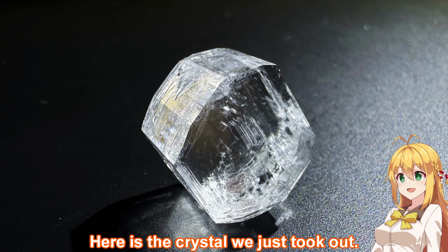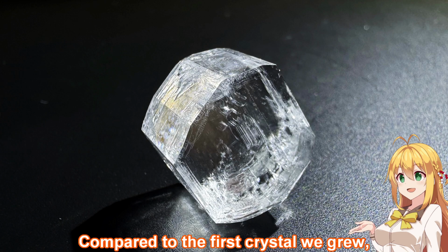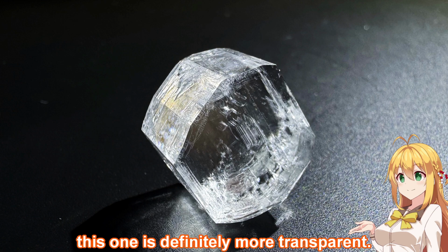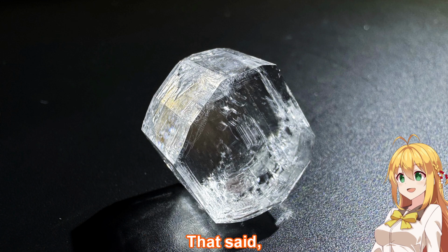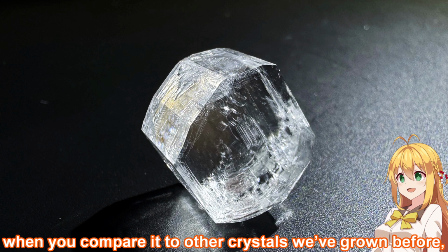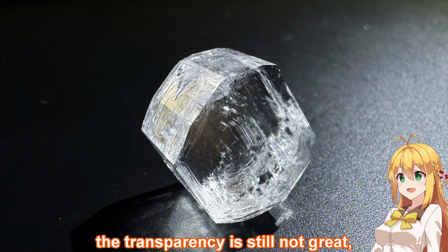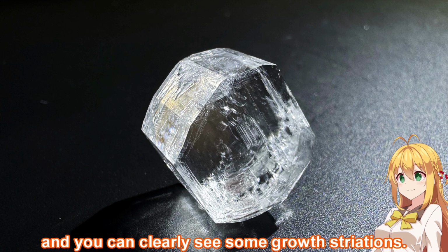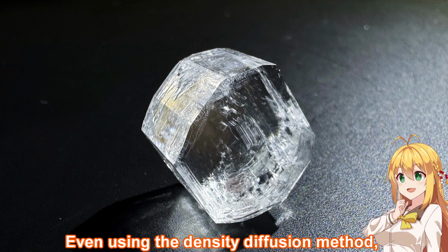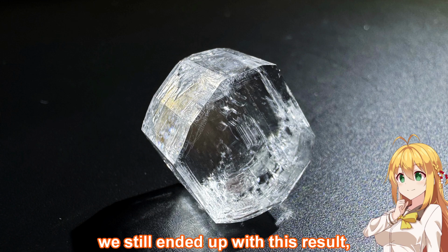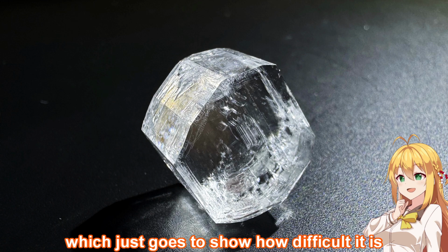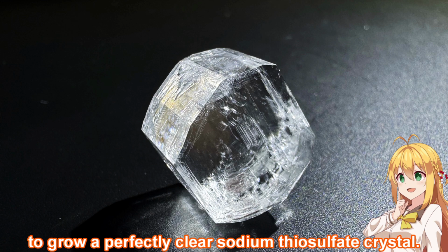Here is the crystal we just took out. Compared to the first crystal we grew, this one is definitely more transparent. That said, when you compare it to other crystals we've grown before, the transparency is still not great, and you can clearly see some growth striations. Even using the density diffusion method, we still ended up with this result, which just goes to show how difficult it is to grow a perfectly clear sodium thiosulfate crystal.